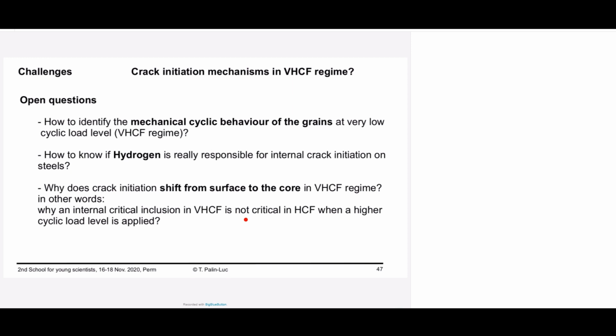So to conclude a little bit with the crack initiation mechanisms, an open question for which I am sorry I have no ideas to propose is how to identify the mechanical cyclic behavior at the grain scale, because in order to model, you need, of course, a cyclic behavior model for your mechanical quantities. And in very high cycle fatigue, the loadings are so small that it is very difficult to measure anything. It is very difficult also to know how hydrogen is responsible for the internal crack initiation in steels, because it is very difficult to measure hydrogen.